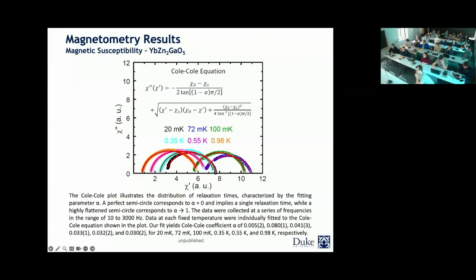If you have alpha close to zero, you will have a single relaxation time, and it shows that the spins are dynamic. If you have a value of alpha that gets close to 1, so for 0 it would be a semicircle, and for getting to 1 it would be very flat, it means that you have multiple relaxation times, which would be an indication of the spin freezing or a glassy nature of the spins.